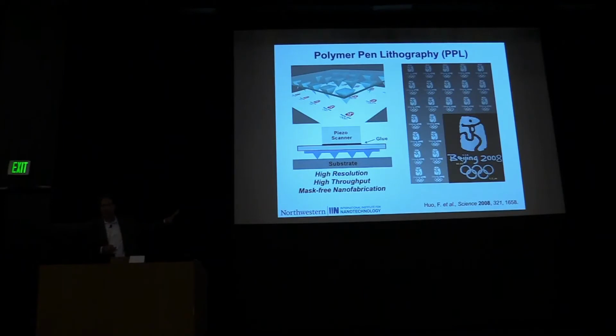And there were a couple things that were striking about this. One was the quality of it. This was literally the second experiment that we still have in the lab. You're looking at this after patterning on gold, and we've etched it using the molecules, the one molecular layer as an etch resist, and you're seeing the raised features that are left behind. But the other thing that was amazing is the resolution. This was done at sub-100 nanometer, 90 nanometer resolution. This was done at 600 nanometer resolution.